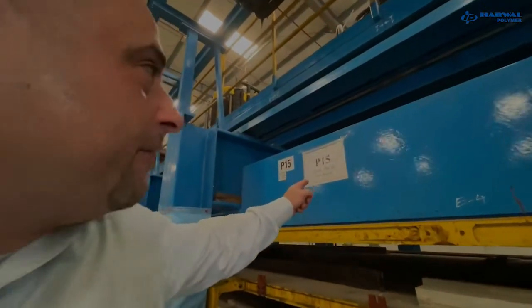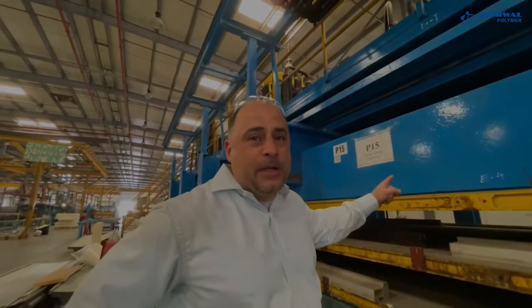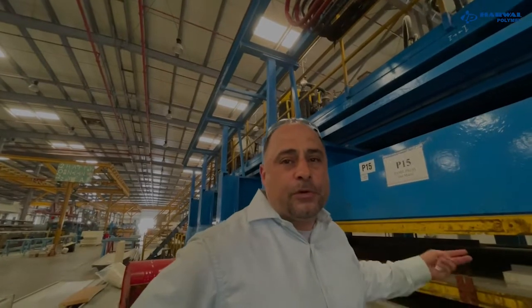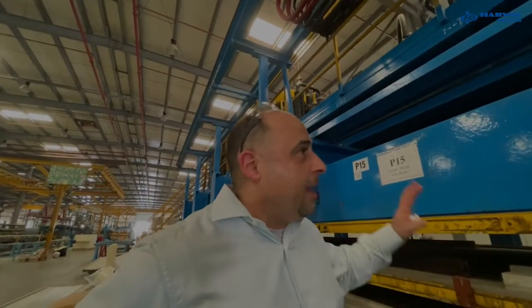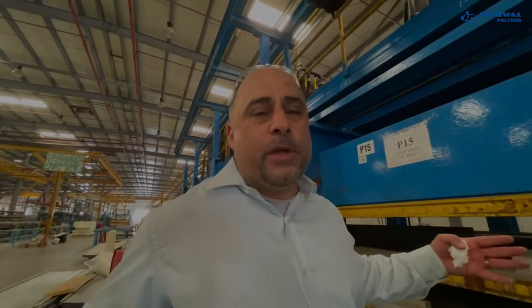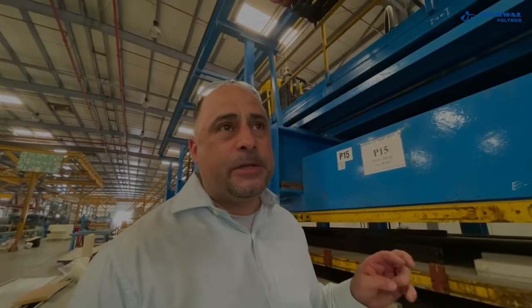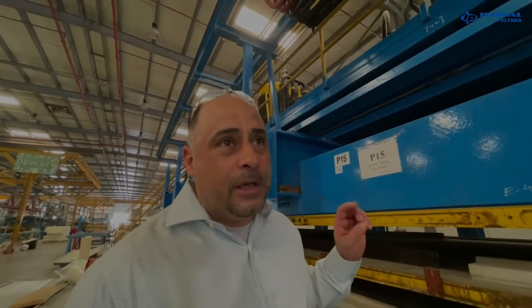As you can see, we are sitting in front of our 16-meter moulding press. On this press we can manufacture panels for cold storages, refrigeration trucks, and housing. We test our formulations for the longest length, the most width, and the most thickness. On this press we can make any panel up to 16 meters in length at a thickness of 200 millimeters. This is where we test any new development — whether PIR, PUR B2, or PUR B3 — under stringent conditions before rolling out to customers.